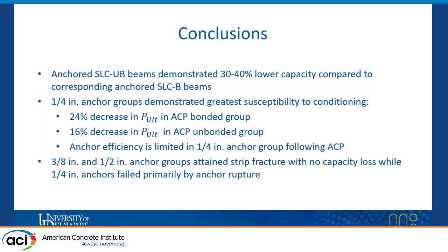And lastly, the 3/8 inch group and the 1/2 inch group didn't demonstrate any susceptibility to the effects of hygrothermal conditioning. However, they were still able to fail in strip fracture, whereas the 1/4 inch anchors, which did demonstrate susceptibility, failed primarily in anchor rupture.